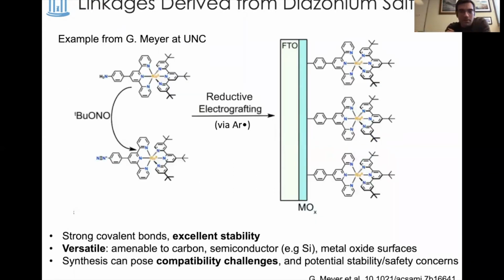Another widely used approach is to use diazonium salts. And this was first looked at especially on carbon materials. So a diazonium would be installed on the periphery of a transition metal complex or catalyst, and then it would be grafted onto a carbon material, usually electrochemically. And so it turns out this is more general than I knew, certainly more general than just carbon. This works for some metallic electrodes as well as semiconductors and metal oxides.